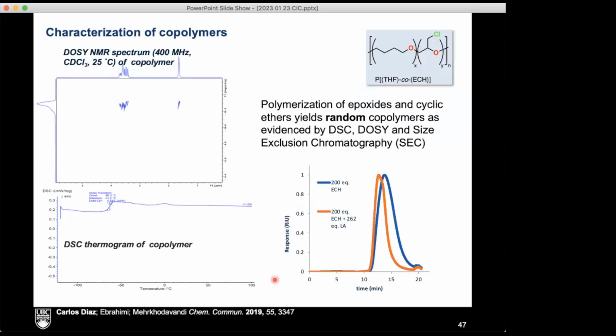He was able to then look at the nature of these polymers, and the DOSY, for example, the DOSY and the DSC show that these are very much random copolymers. So you see one peak in the DOSY, and one rise in the DSC. So clearly one polymer, and these are random copolymers. And that's actually shown from the GPC as well.